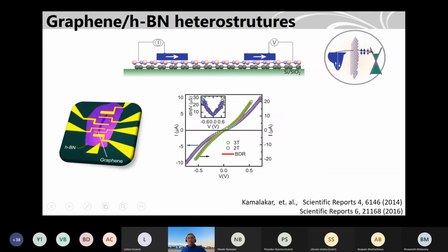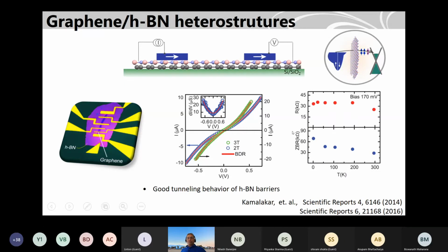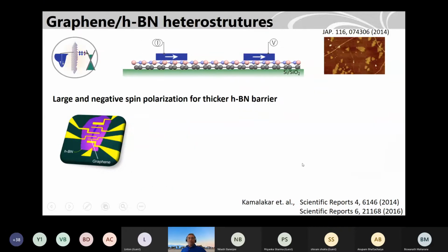And we get very good tunneling, nonlinear IV curves. So when you go to high voltage, and we plot the zero bias resistance, this is not much temperature dependent. So the quality of the tunnel barriers is very good. But what about the spin transport?